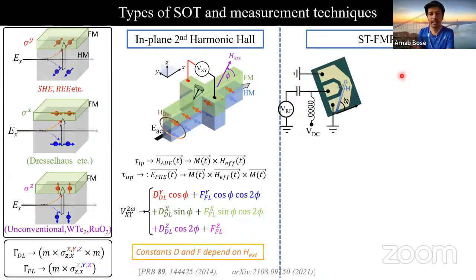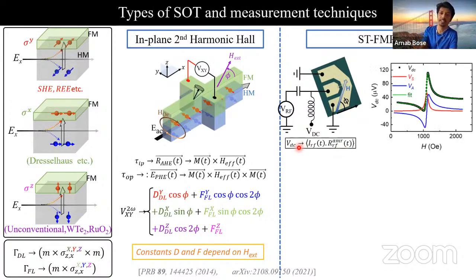STFMR is very similar to in-plane second harmonic Hall. In this case, instead of applying low frequency AC current, we apply radio frequency current in the system. Again, there are various current induced torques, which drive the magnet into resonance. Its magnetoresistance changes due to AMR. Now we have a homodyne mixture of the radio frequency current and radio frequency resistance, which together produce a DC voltage that we experimentally measure.